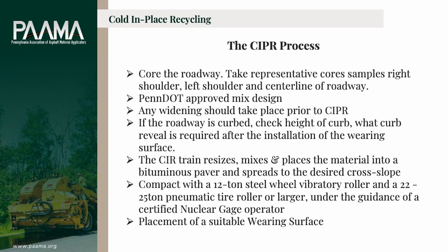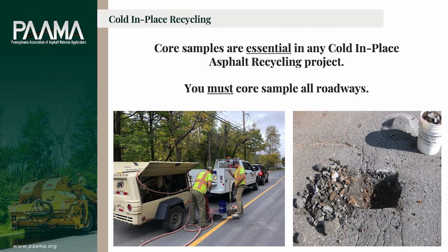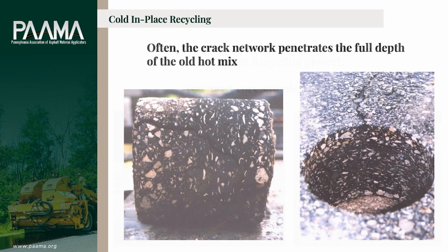Placement of a suitable wearing surface, whether that's a chip seal or a hot mix asphalt or an ultra thin or whatever it is, the agency needs to establish that and put that into the bid specs. Core sampling, as I said, is essential. Most of the cracks in a roadway go, as you can see on the left here, the crack starts at the top and goes all the way through the core.